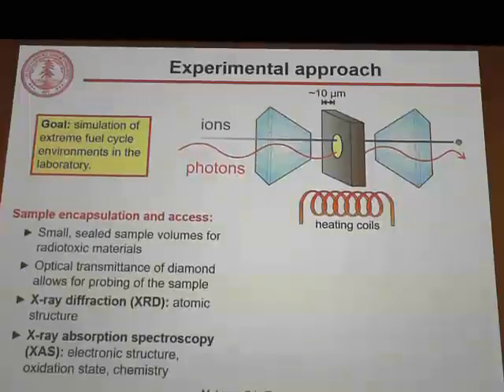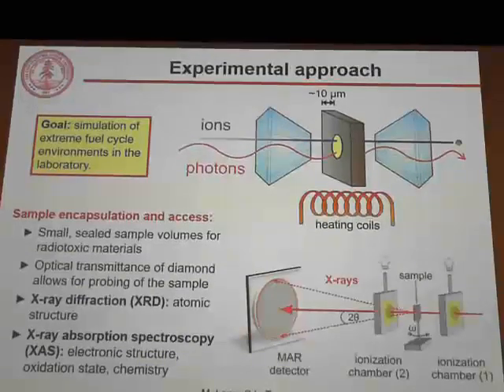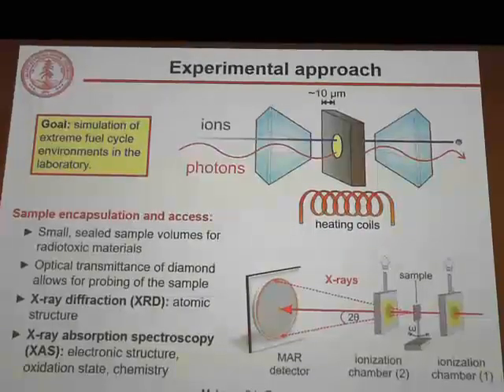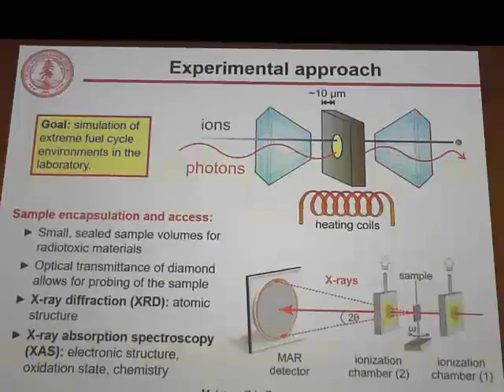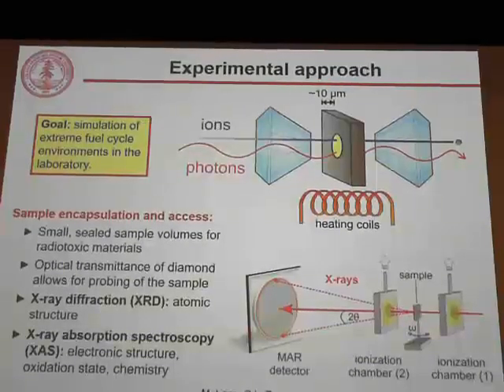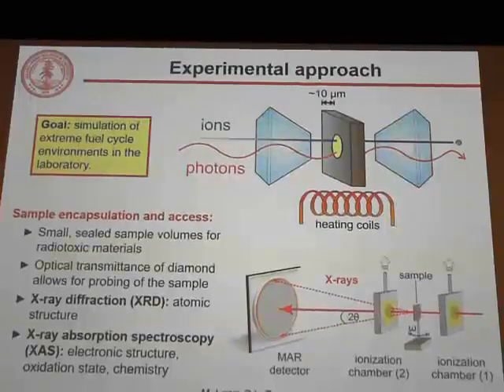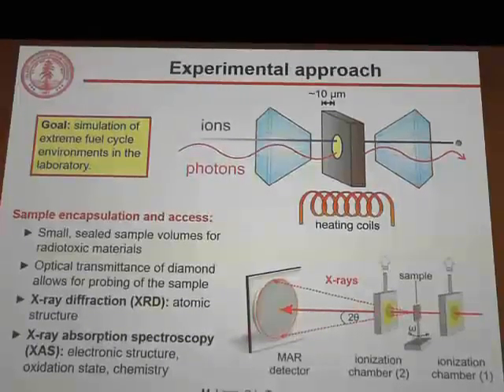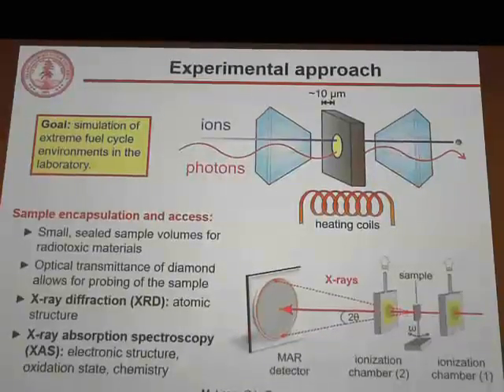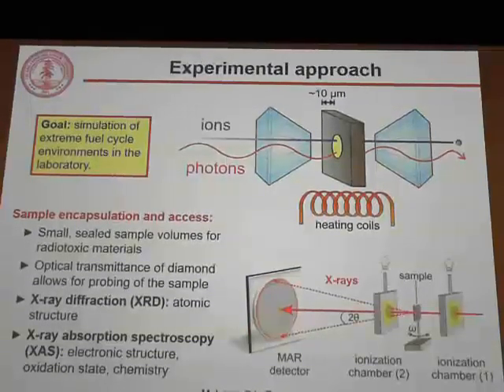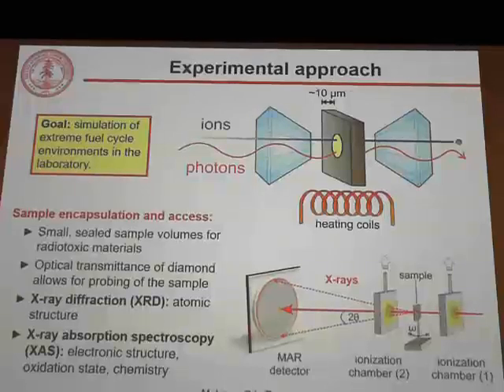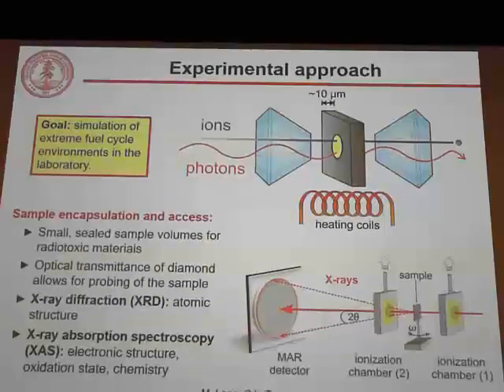And also they're transparent. So for characterization, this is nice because most of my characterization I do at synchrotron facilities where I pass an X-ray through my sample, and then I can use the diffraction to learn about changes to the atomic structure in extreme environments. And I can put ion chambers behind and in front of the sample to measure the absorption of X-rays, which tells me about the electronic structure, changes to oxidation states of elements, and the chemical changes that are being undergone by this material.